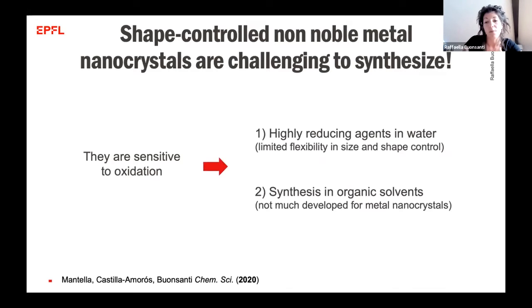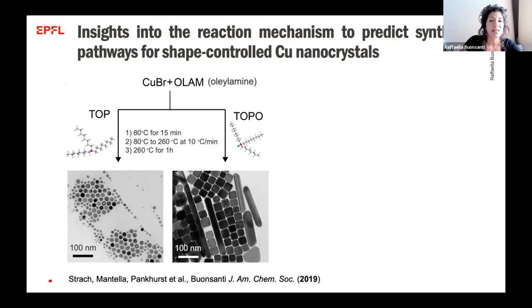So we have to start thinking more about synthesis in organic solvent, and we need to start learning how to develop it in order to shape non-noble metals and copper. So we started with two hints from the literature, which indicated that the synthesis of copper bromide and oleylamine in the presence of trioctylphosphine forms spheres, and the synthesis in the presence of trioctylphosphine oxide forms cubes.